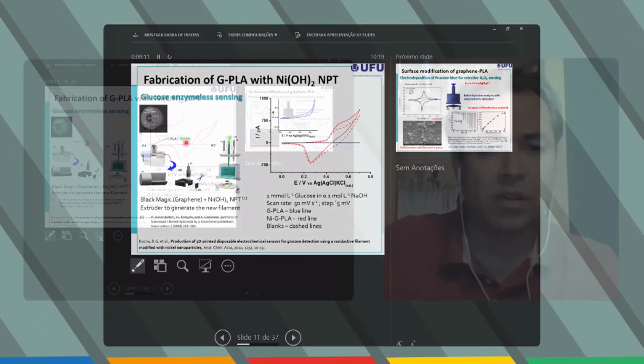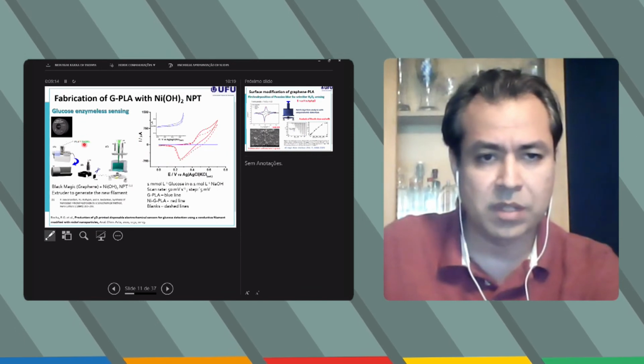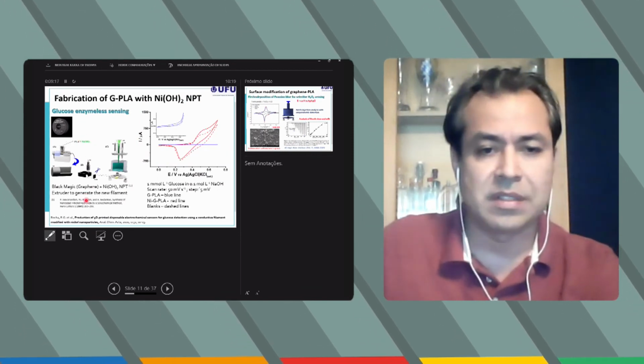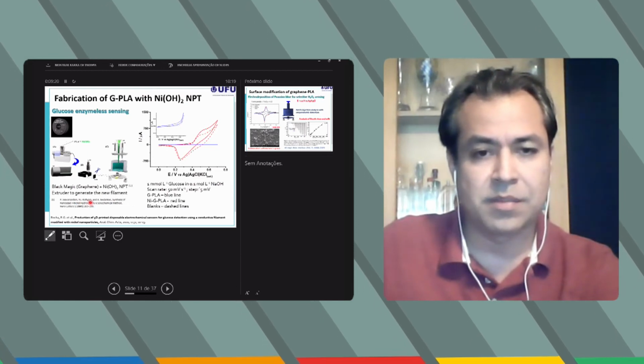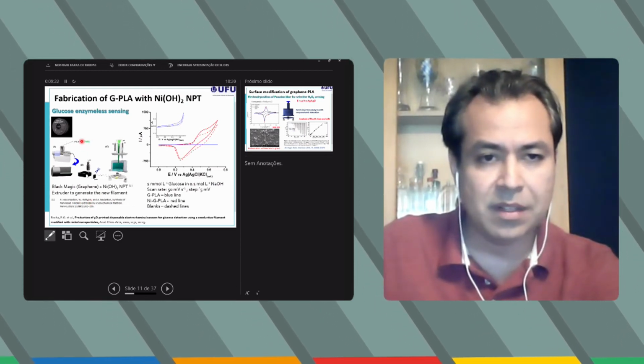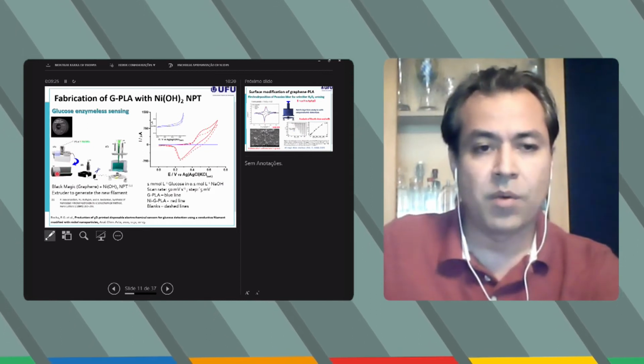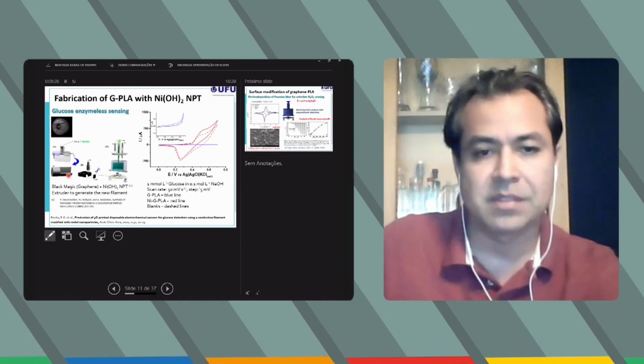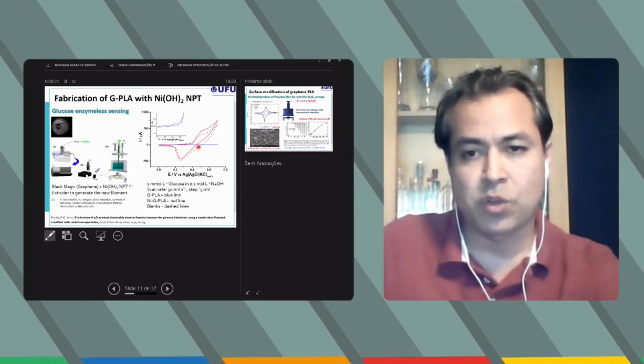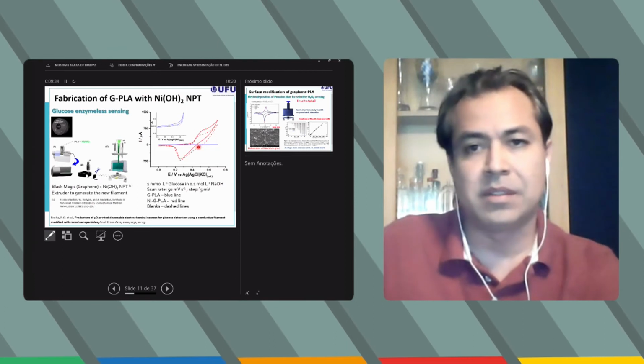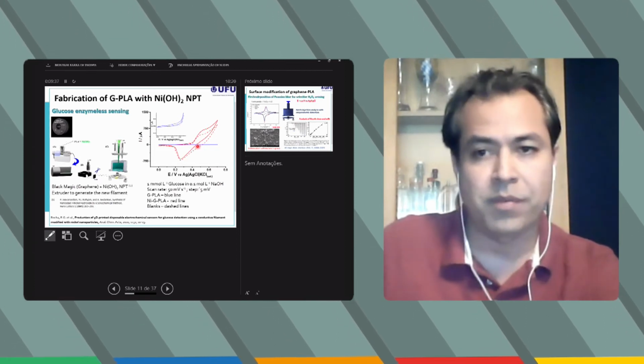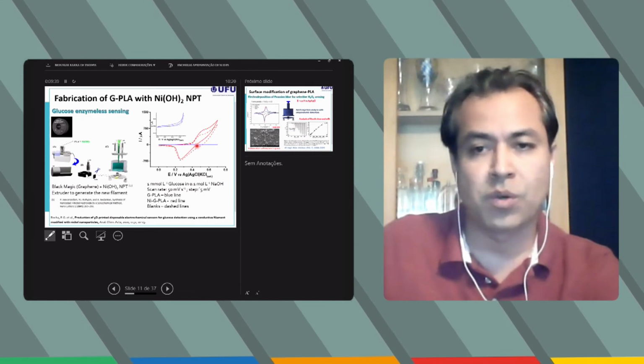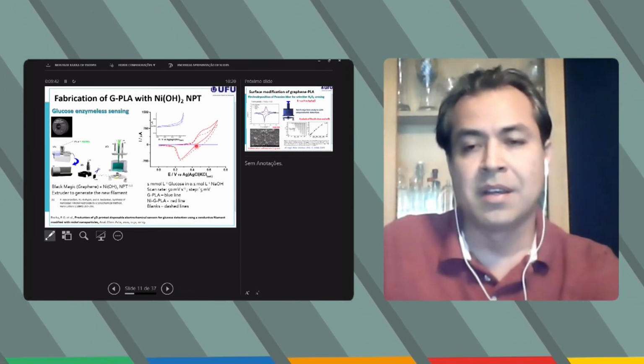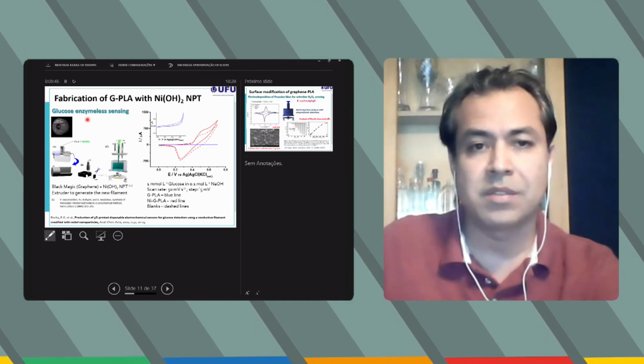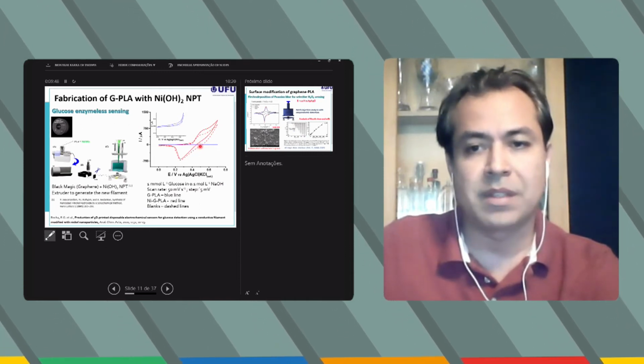Another possibility we also showed is the incorporation of nanocatalysts. For example, this one is nickel hydroxide that was synthesized following this paper. The idea was to mix this nanocatalyst with graphene PLA to produce a filament containing this nanocatalyst. And this voltammogram shows that the modified filament used for 3D printing was able to provide a very interesting electrode for the detection of glucose without enzymes. So it's possible to perform the determination of glucose.